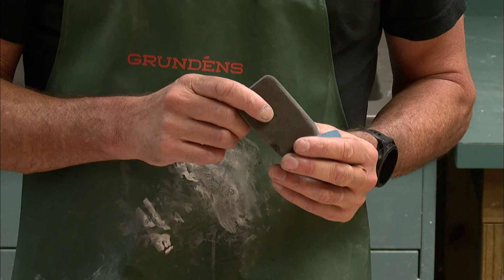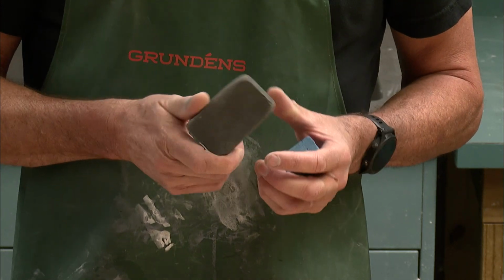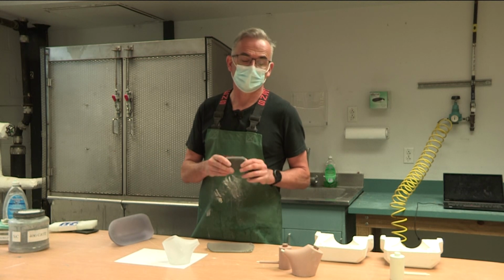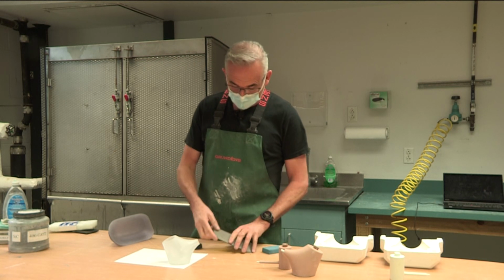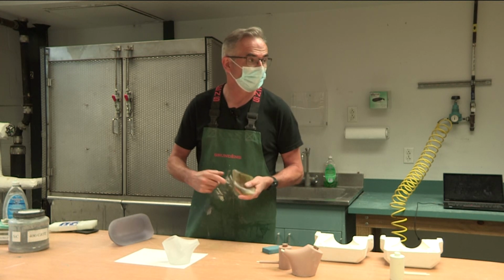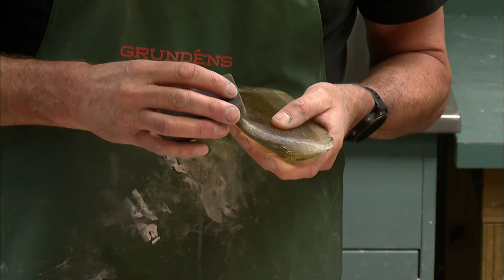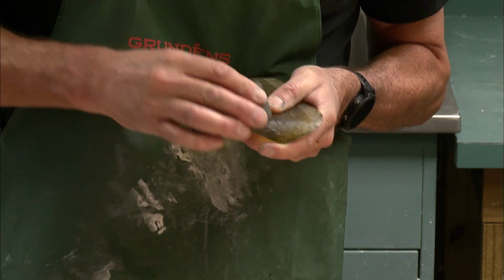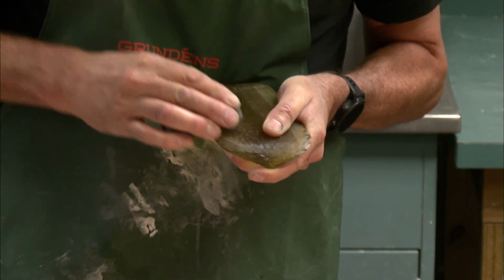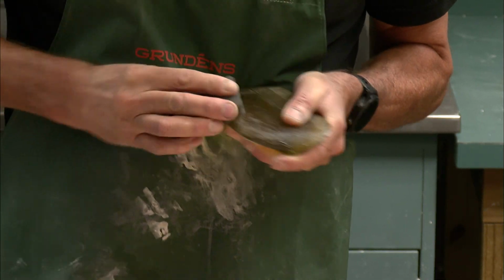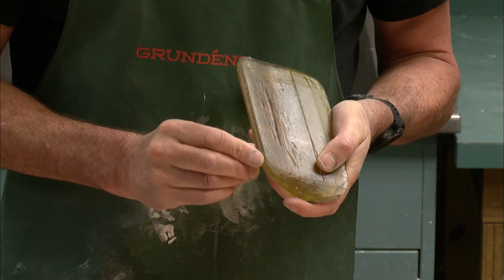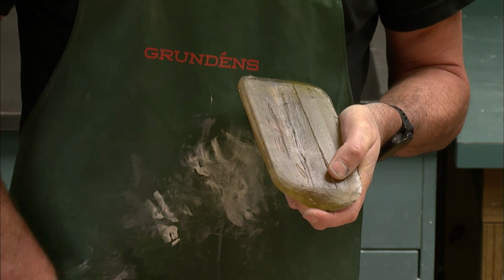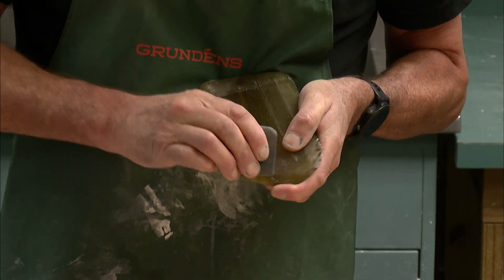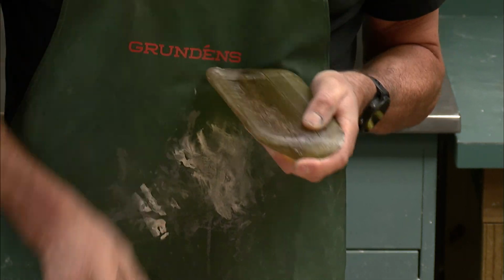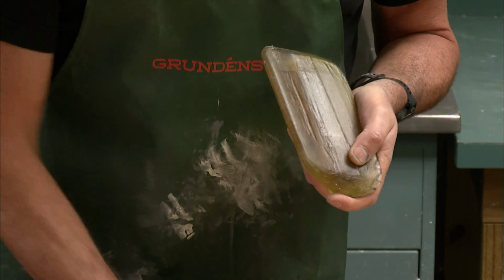They're called sandflex blocks. They're very similar material to the silicon carbide, but in a rubber block. And you can use that to just buff the surface of your glass. So if we have a look at this little surface here, you can see this kind of schmutz, technical term, schmutz, on the surface there. If I just give it a little bit of a buff with one of these blocks, it can really just blend it in. That only takes, as you can see, a couple of moments, and then it's a little bit matted, but there's a finer block that I can use to even out those surfaces. So it's just a bit of a cheat, and it's a really great way to finish up some surfaces.